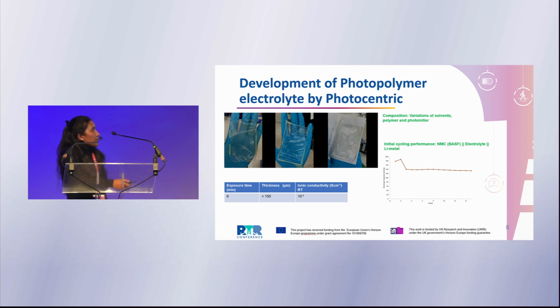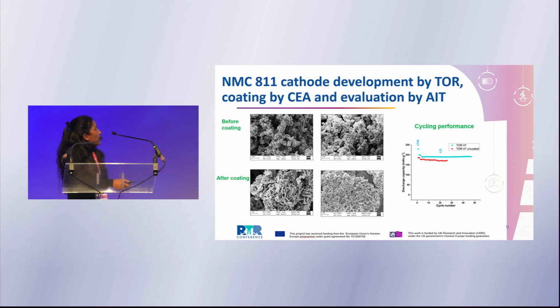And again, this cell was tested with commercial NMC and lithium metal. As you can see, the performance is still promising, at more than 120, which is really good performance for state-of-the-art electrolyte materials. So the next step of this project focuses on the development of cathode and catholyte formulations, which is led by 3 different partners. And here the cathode material is developed in the project, not bought from commercial ones.